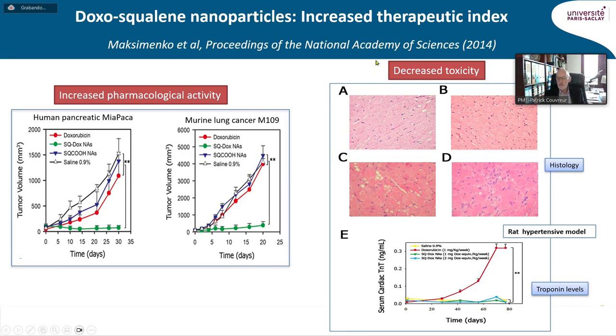And from the point of view of toxicity, we investigated the toxicity on the rat hypertensive model. And you can see here in red that after administration of the doxorubicin as a free drug during 11 weeks, once a week, at the dose of 1 mg/kg body weight, there was a huge increase of the troponin, which is a marker of the cardiac toxicity. And at the end of this treatment, by taking some cardiac biopsies of those animals who survived the cardiotoxicity of the doxorubicin, by looking at the histology, you can see that there was a very, very strong vacuolization of the cardiomyocytes. And this is also, of course, a marker of the toxicity of doxorubicin.